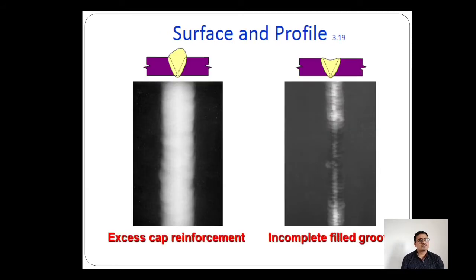So friends, if you see this kind of discontinuity in radiograph terms, on the left side of the figure you can see the excessive weld reinforcement. You can see the welding bead in the radiograph looks very light. Once it shows very light, it means the welding reinforcement is too high. And in the second picture, on the right side, incomplete filled groove, it means in the radiograph the welding bead is too dark. So you have to understand that the welding profile is less than required.